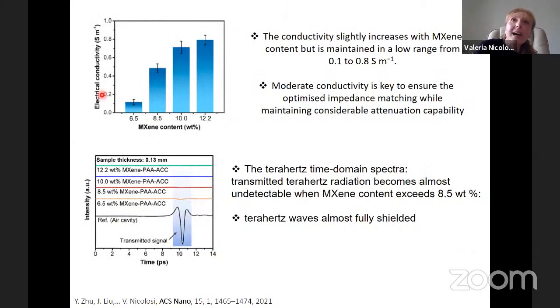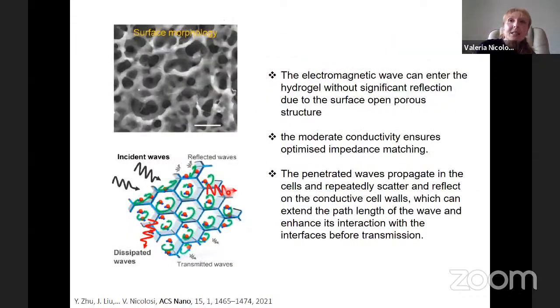You can track how we can make it more and more electrically conductive, increasing the load of MXenes. And you can see how good this hydrogel is at shielding terahertz radiation, for example. Only 6.5 weight% of MXenes is already blocking almost all the terahertz radiation here. And by 8.5 weight% of MXenes, you get no radiation leaking anymore. This is, in our opinion, because you get this nicely porous structure: the terahertz radiation gets in, starts penetrating and getting scattered and reflected, and only a very tiny little bit is transmitted away. The rest is dissipated.